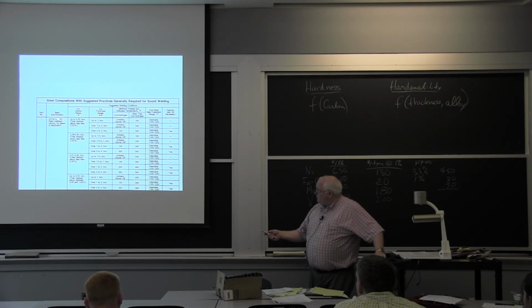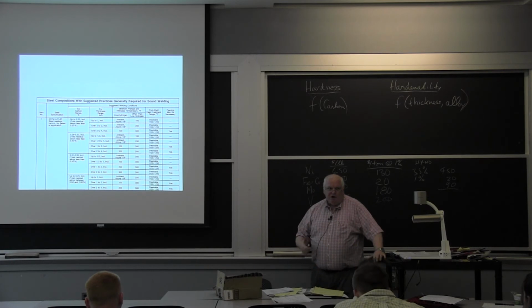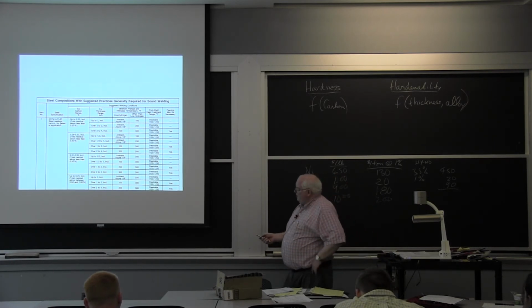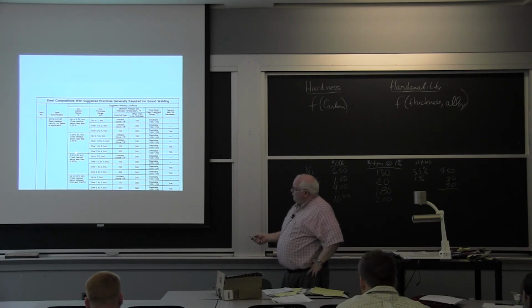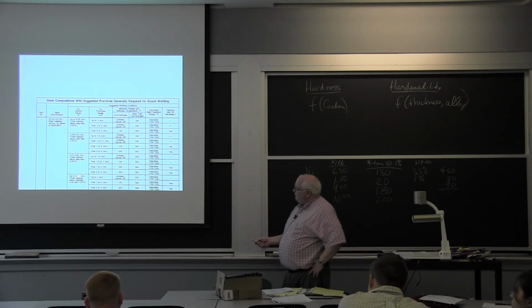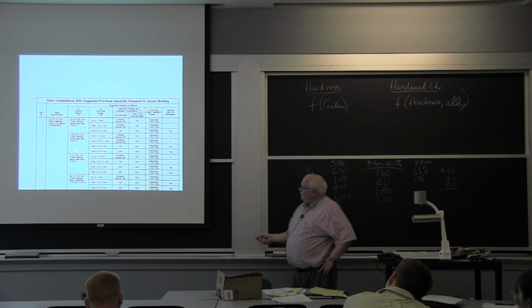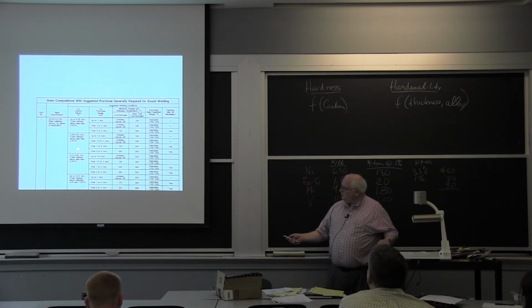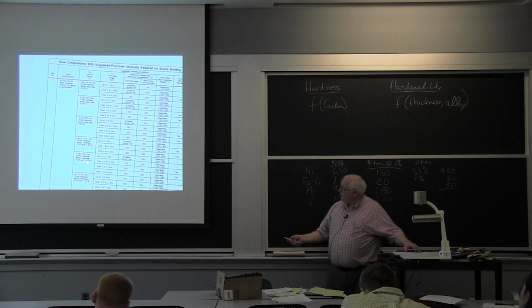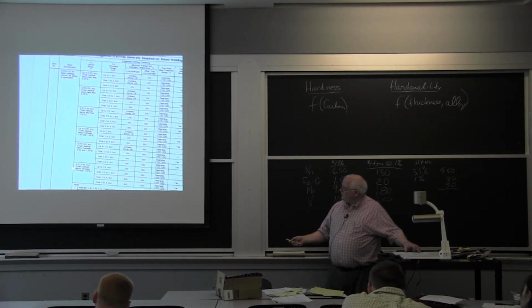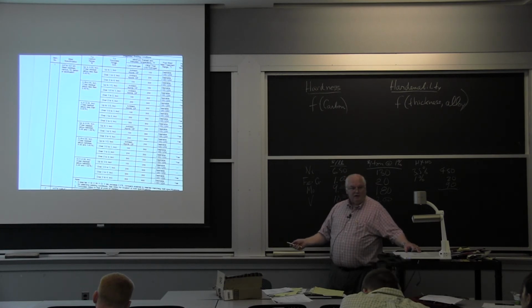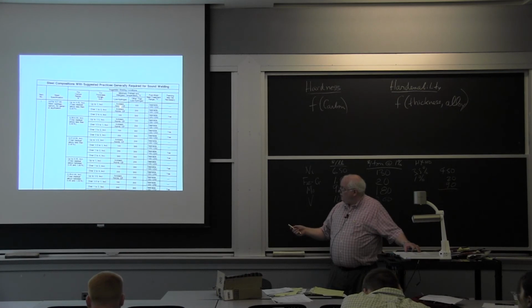This particular steel, which is ASTM A27 steel castings, this is your garden variety, cheapest steel casting you can think of. Up to 0.25 carbon, so that's low carbon. These castings come in medium carbon too, and so you have to break this up into low carbon and low medium carbon and medium carbon. And down here you can have some residual alloying elements, and you have to take into account those. And in fact, you're going to find that here, if it's nice low carbon and relatively thin, I don't even have to preheat it. It just says I have to be above 10 degrees Fahrenheit.